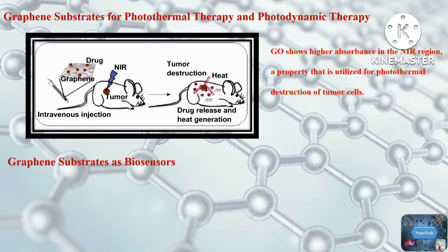Photodynamic therapy is a novel treatment for cancer which combines photosensitizer-mediated targeted killing. Upon light activation, the photosensitizer molecule gets excited and induces the formation of reactive oxygen species that cause irreversible damage to cancer cells. Researchers have used graphene oxide for treating cancer cells via photodynamic therapy by loading the photosensitizer onto folic acid-conjugated graphene oxide via hydrophobic and pi-pi stacking, showing effective killing of MGC-803 cancer cells.